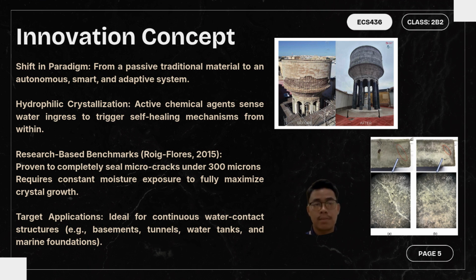By using engineering principles of hydrophilic crystallization, the material gains the autonomous ability to sense water ingress and heal itself from within, perfectly aligned with the technological advancement of IR 4.0, which is Industry Revolution. According to a study by Roig-Flores, this technology is exceptionally innovative because it can completely seal microcracks under 300 microns when constantly exposed to moisture.